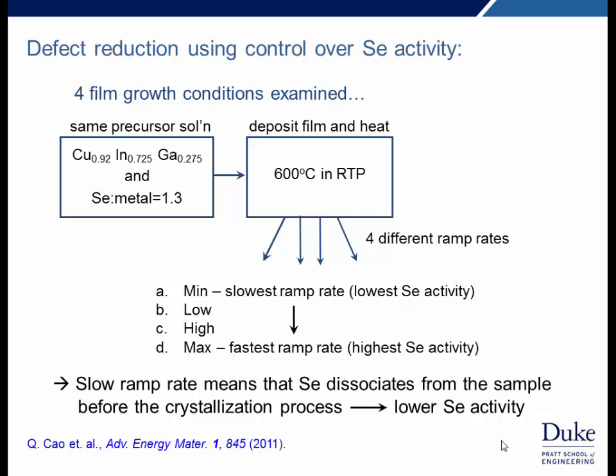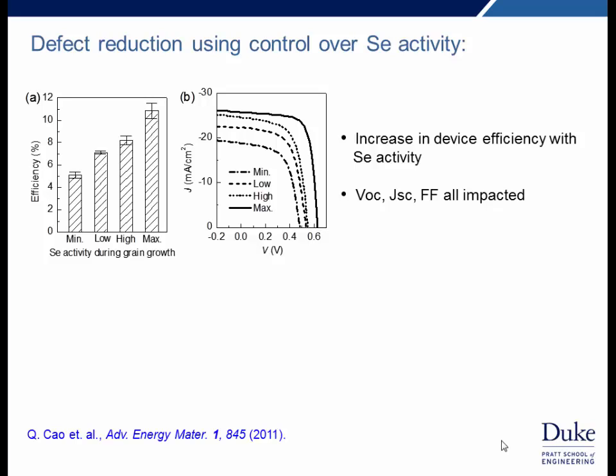By varying the heating rate, we're also varying the effective selenium concentration in the film during the crystallization process. Namely, if we heat slowly, the extra selenium has a chance to evaporate from the film before we reach the crystallization temperature, and if we heat fast, this is not the case. And this has a big impact on device performance. Here we can see slow heating, low performance, fast heating, high performance.